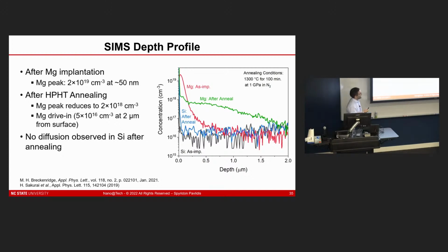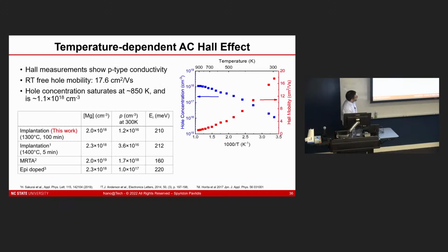And I would also argue that there may be opportunities here to leverage this for device fabrication in the future, kind of doing similar things to what people did with silicon that we maybe weren't thinking about when we moved to something like silicon carbide. A little bit of Hall data here. I'll just point out that once we do this activation step, we're able to see high hole concentrations as well as high mobilities. And if you work through the literature and these numbers in this chart here, you'll see that the implanted p-GaN layers have mobilities on par with what you get with epitaxy. So we're able to achieve high quality material there as well.